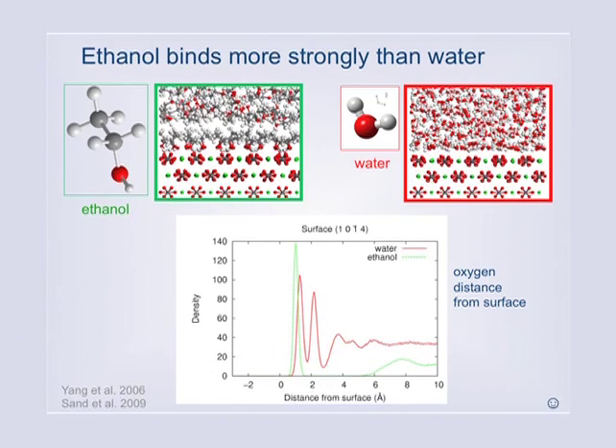Here we see an ethanol layer, here we see a water layer, and here we see the distance, the oxygen distance from the surface. So ethanol is green, and here's the surface over here where it says 0. So ethanol is more tightly bonded than water with its oxygen pointing toward the surface, or water with its oxygen pointing away. So in either configuration of water, it's not as strongly bound as ethanol.